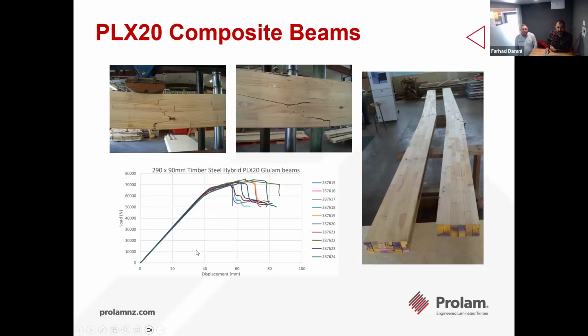So what you can see here, there is a good consistency in the results for these different samples that we have tested, both in terms of the stiffness and strength. And you can see there is a little bit of ductility as well, so you don't get a sudden brittle failure. So which is making a good point of difference between this composite beam compared to simple Glulam beams. Which is good, for example, for collapse prevention or life safety aspects in our design when we want to consider those in our design targets as well.